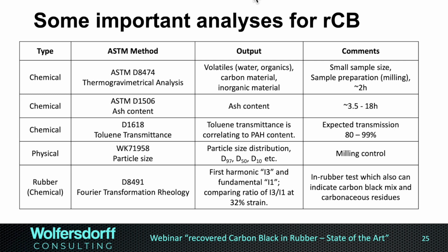Toluene transmittance, quick test, very easy to do. Expected transmission for a good recovered carbon black is 80%. Really very good recovered carbon blacks are getting close to 99% transmission, which means that the toluene didn't extract anything meaningful out of the recovered carbon black that is hindering the light transmission. Meaning there's no or very low PAH content, which can be tested, of course, by gas chromatography and mass spectroscopy, but we won't do that as an inline test or as a frequent test in the production.